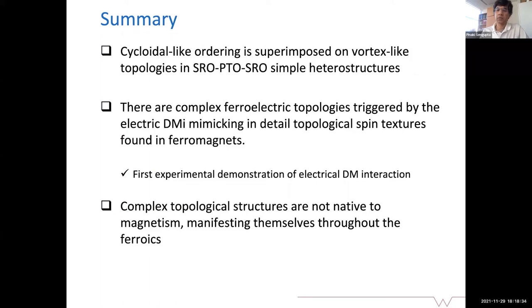And again, what you have seen there, those tiny vectors, which show we have a vortex like this and a vortex like this, you won't see them. So practically, we measure the position of the atoms by transmission electron microscopy. We reconstruct the unit cell, and we reconstruct what the polarization vector would be from exactly this distortion. The distortion can be as small as 20 picometers, which is a challenge to measure. So you have to have a damn good microscope. So it's a complex measurement, not something you can measure easily.